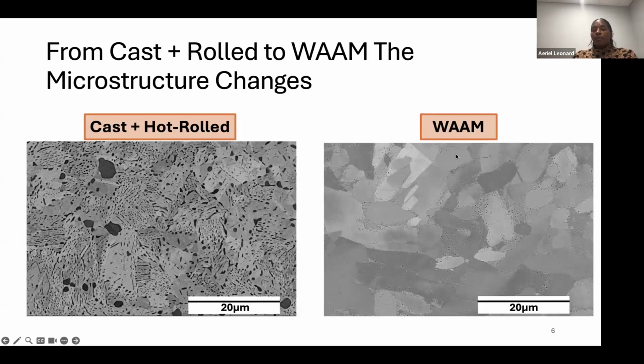You do not see kappa 1 in the wire arc additive manufacturing condition, and that's because the solidification rate is much faster. And so you don't have the opportunity to precipitate out that phase. It's very good from a mechanical property standpoint because this is a brittle phase, and a lot of crack initiation usually occurs at these large kappa 1 phases.